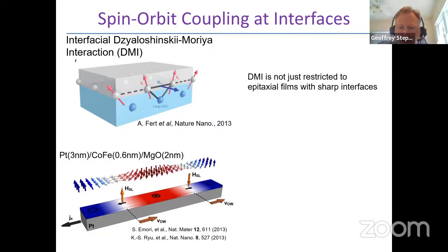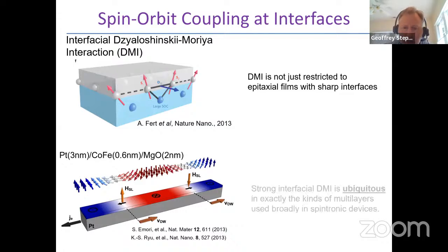And this can generate spiral spin textures. It can generate chiral domain walls that can be readily driven in these kinds of structures by electric current by virtue of the spin Hall currents that are generated in the heavy metal under current flow. And these kinds of interactions, it turns out, are ubiquitous in exactly the kinds of bilayers and multilayers that are broadly used in spintronic devices. So this makes these kinds of materials, if one can engineer them appropriately, both ideal to study the fundamental phenomena, but potentially of practical use because they could be integrated into devices that allow a readout through something like a magnetic tunnel junction.